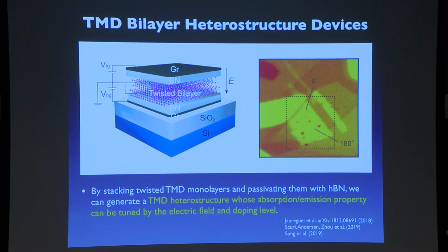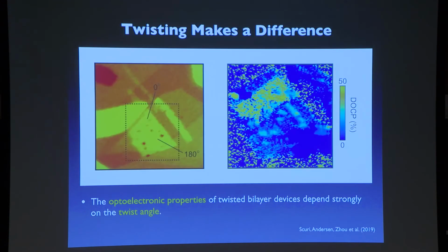The most important thing is the following. It turns out that the twist degree of freedom, the twist angle that you introduce, has a profound effect on the properties of the materials. Without going into detail, this shows one example of that. This is the same device. One region was two stacks, which makes a 0-degree angle. The other region is two stacks making a 180-degree angle. And then you can actually measure one particular optical property, and you can see they are entirely different. We'll get to that in a little bit. But twist angle makes a humongous impact on the optical properties of these materials.